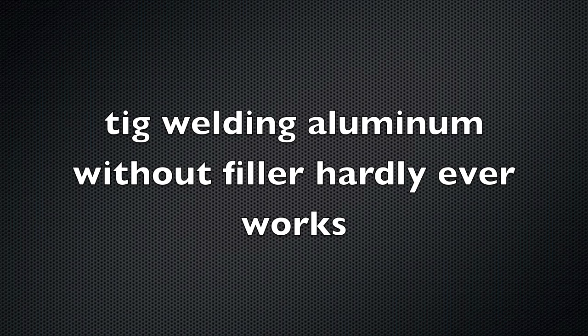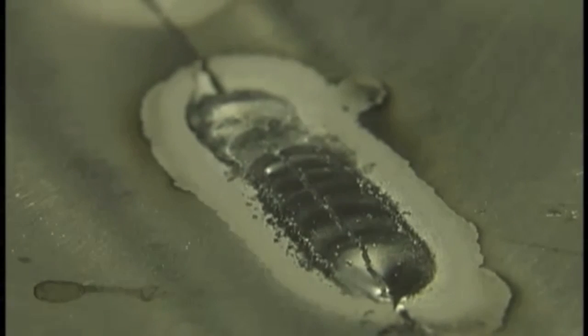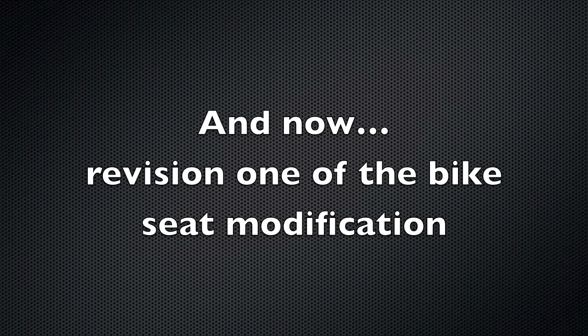Another tip that is pretty obvious, but hey, if you haven't done it before, you need to know this. Welding aluminum without any filler wire hardly ever works. Aluminum is just hot short. It's weak when it's hot, and all those contractile and shrinkage stresses while the outside metal is resisting and expanding, this causes problems. See that crack open up right in the middle of the weld? Pretty typical.